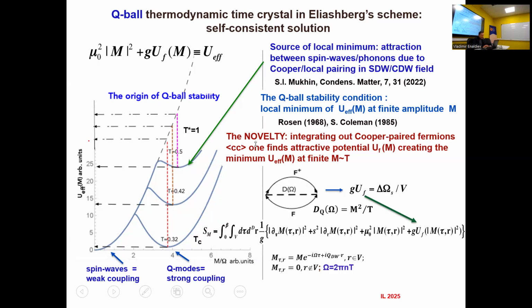What happens is the following: above some temperature, where there is no solution of the self-consistency equation, we have just this term mu sub 0 squared, and if you neglect the derivative, you have a homogeneous, actually quantum oscillator, with a parabola where the energy is parabolic as a function of amplitude. Now, when Cooper pairing appears, this UF becomes negative, and it makes an extra minimum, which is not at zero amplitude, but at finite amplitude. This first happens at some temperature T star, which we will see how it looks like. And then when you go down in temperature, this minimum becomes deeper and deeper.